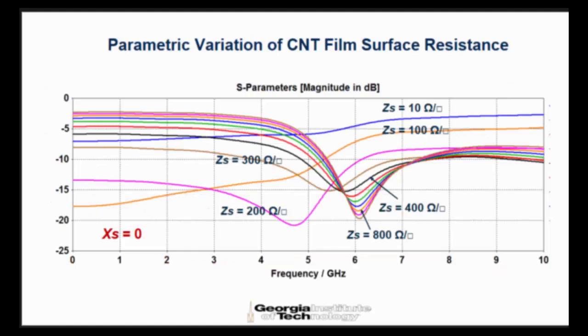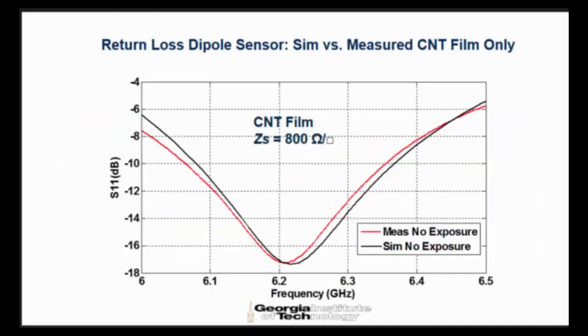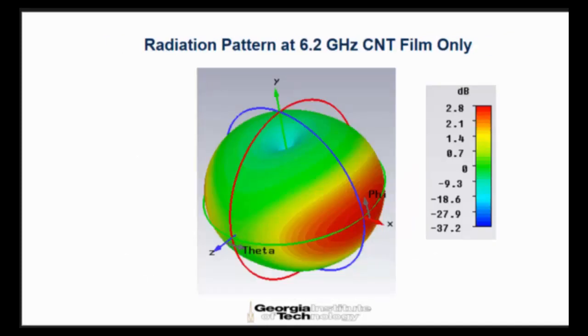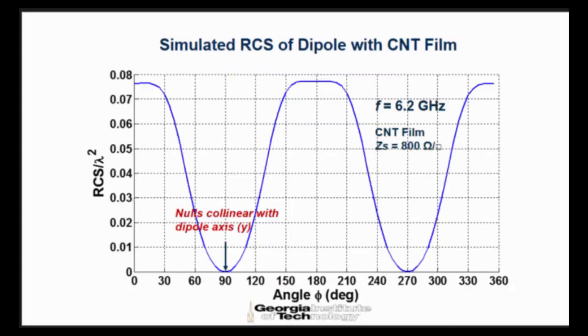So here I'm plotting some results at very small resistors. You don't have any resonance, but as you increase the resistance value to around 800 ohms, you get a very good resonance. And this is an example of simulation versus measurement when there is no gas exposure. This is a simple experiment without any gas exposure. We get very good agreement with a resistance of 800 ohms. And this is the radiation pattern, about 3 dB gain. Radar cross-section clearly shows the expected pattern, the oscillatory behavior of a dipole with regard to scattering or radar cross-section. So we get a significant signal, as you can see from here. So a resonant scatterer also gives a resonant response in radar cross-section.